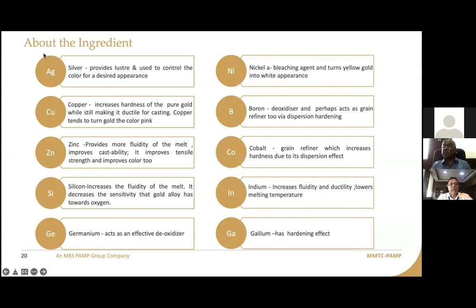Cobalt is a good grain refiner, which increases the hardness due to dispersion effect, and especially for handmade alloys, where you want hardening, you want the work hardening index to go higher as you work, you do add cobalt in a controlled way. Again, if you add cobalt beyond a certain range where it is no more soluble, it can segregate and form precipitates, which will act as a stress raiser and can form cracking also.